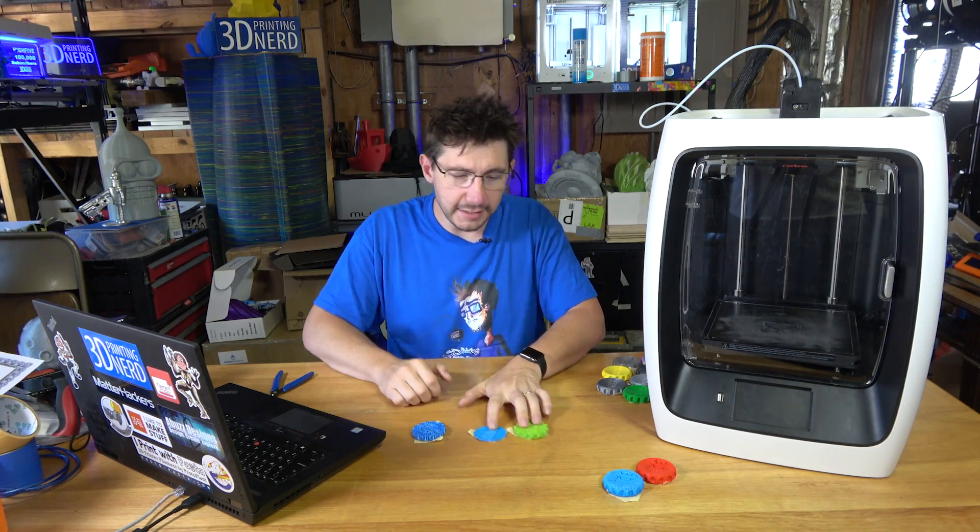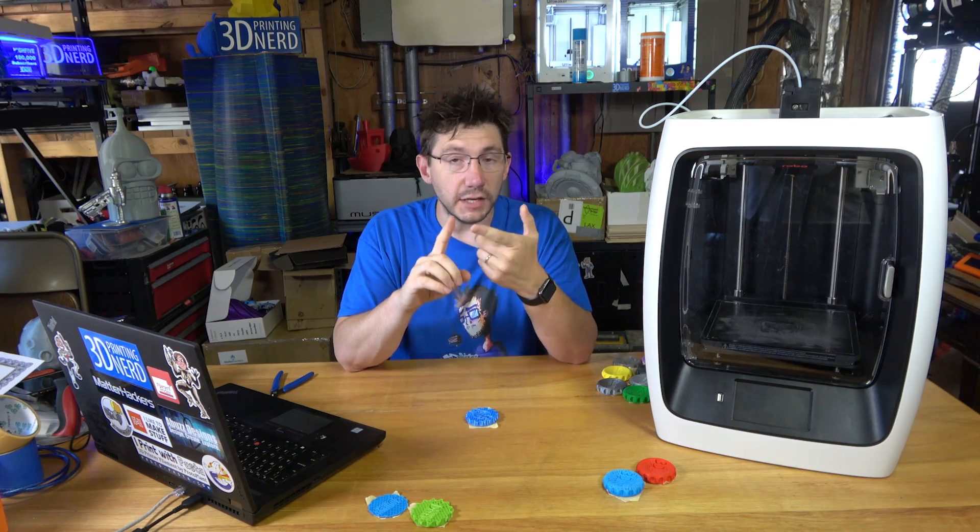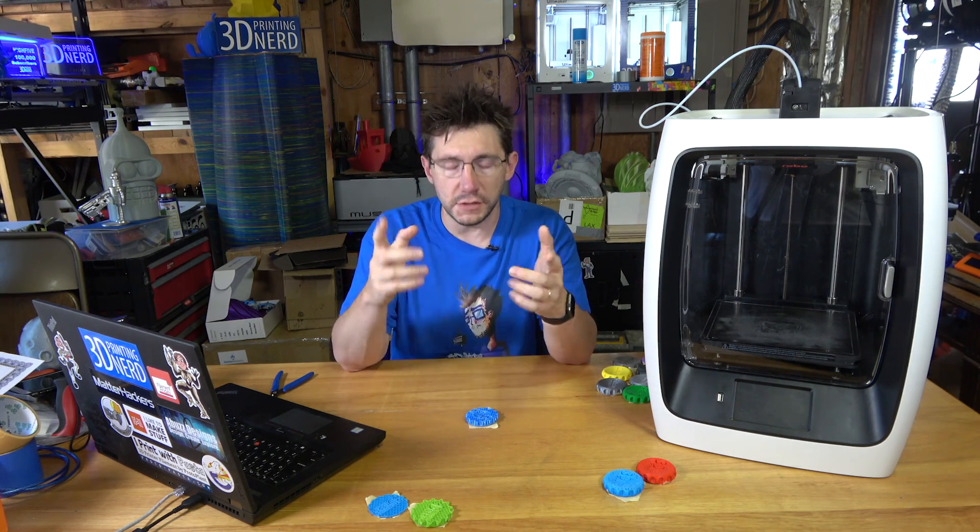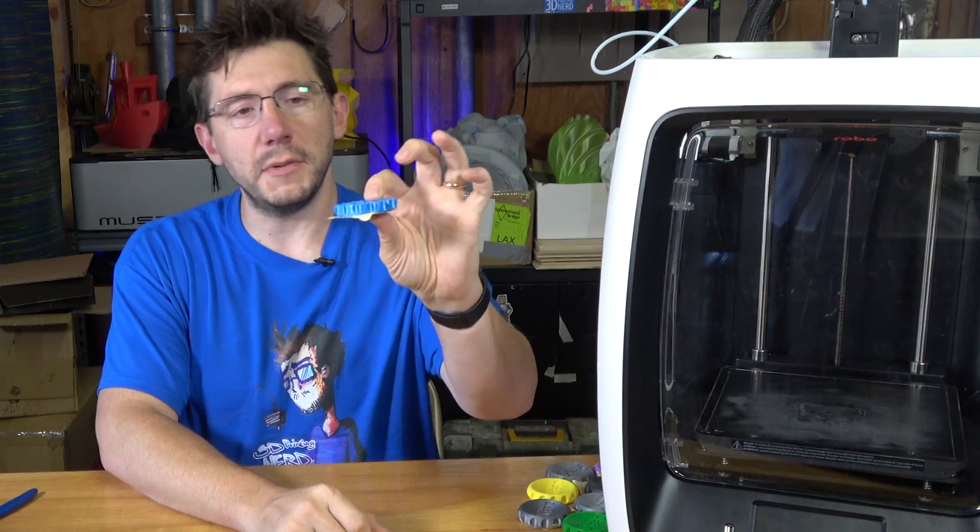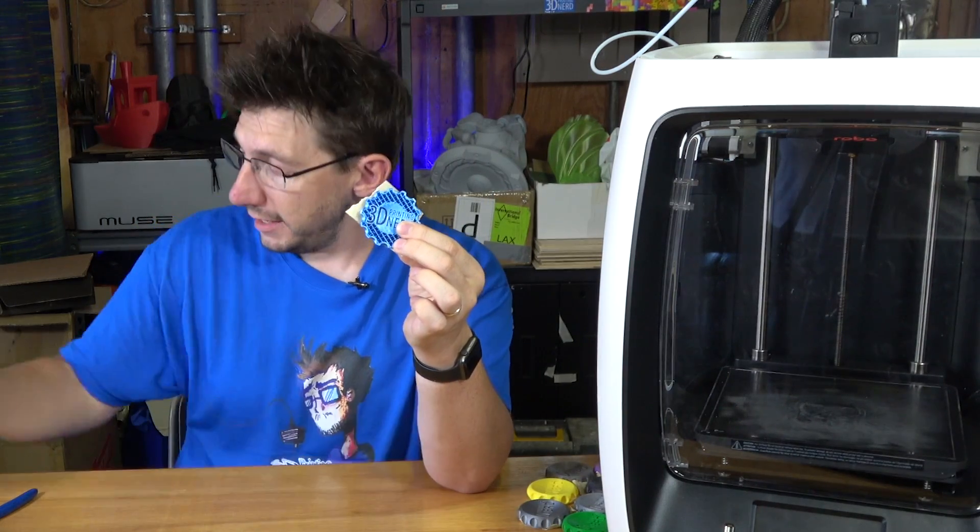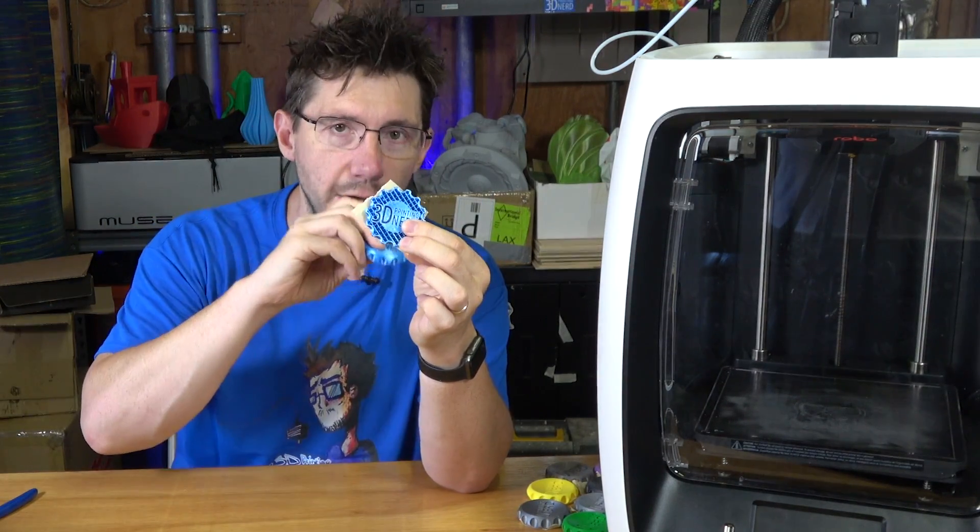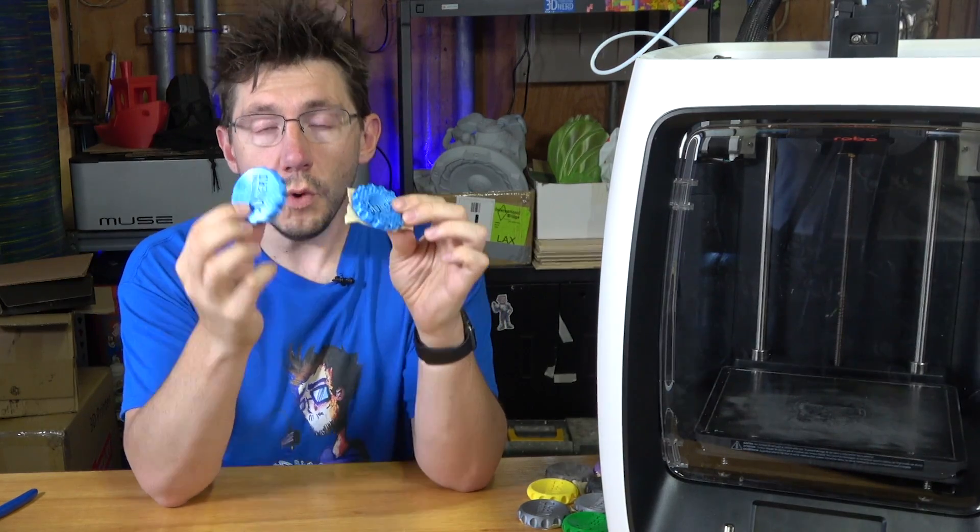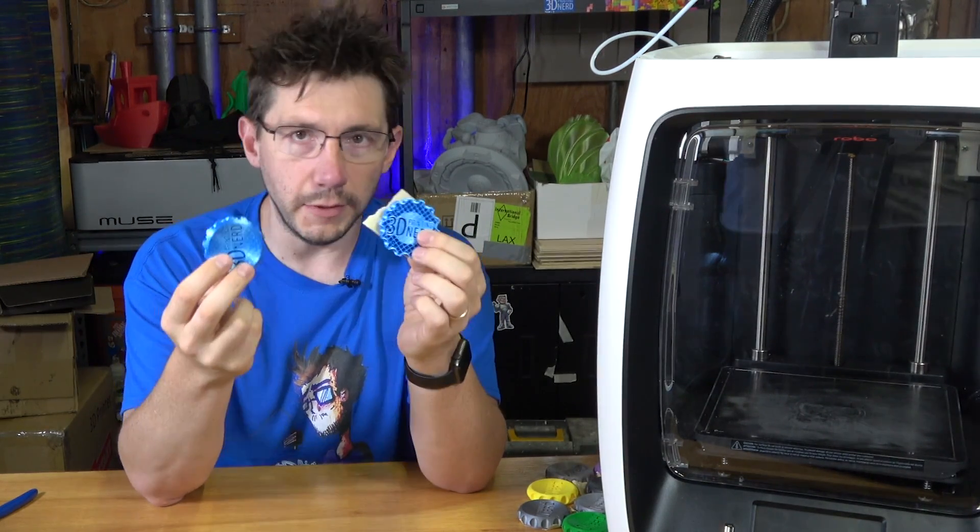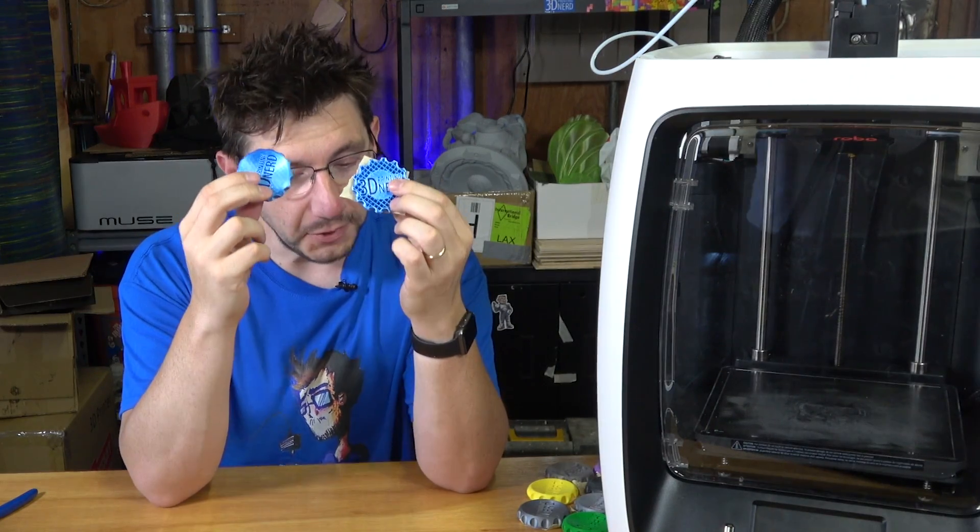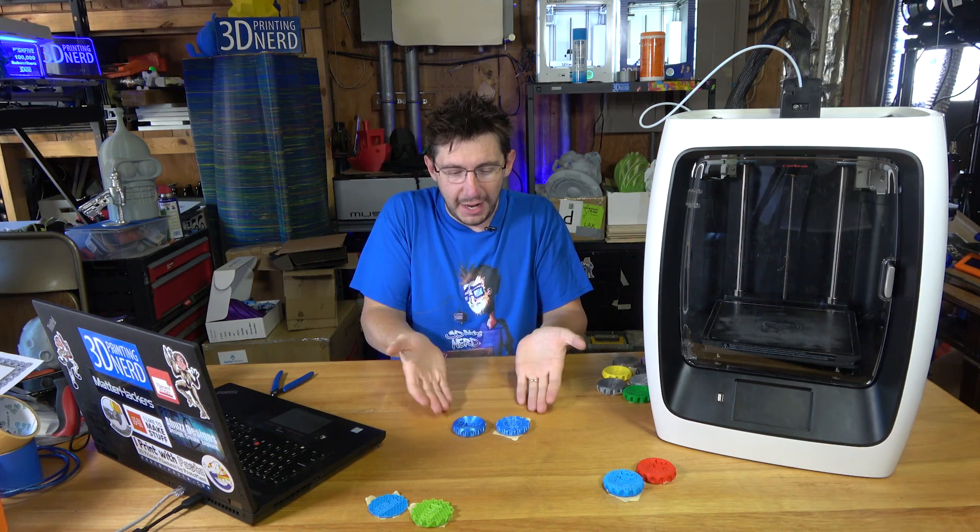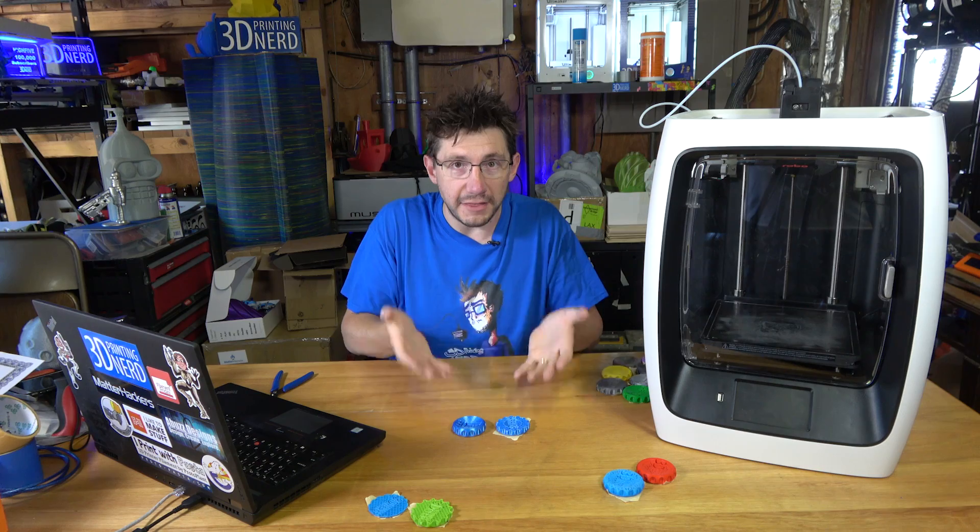So as a test, what I did is I took the metal plate off of the printhead and I figured this would allow the fan in the back to cool the fins properly and to lessen the chance of heat creep affecting the filament when doing the retractions during the print. So this was with the Orb Polymer PLA and this had a blockage. I then, with the front cover off, I printed it again and it worked. There's a little bit of pillowing, but there was pillowing on the others, but it completed the print and it completed it successfully and I had a concept that I think worked.